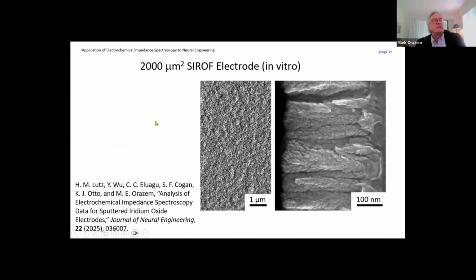So the first ones are relatively large, 2,000 square microns. And this is an image of the surface of the electrode. It is a porous structure. And so if you look at a cross-section, we see that there is a porous layer here. And in fact, a porous electrode model was used to fit this data. And this work was published actually last year in the Journal of Neural Engineering.